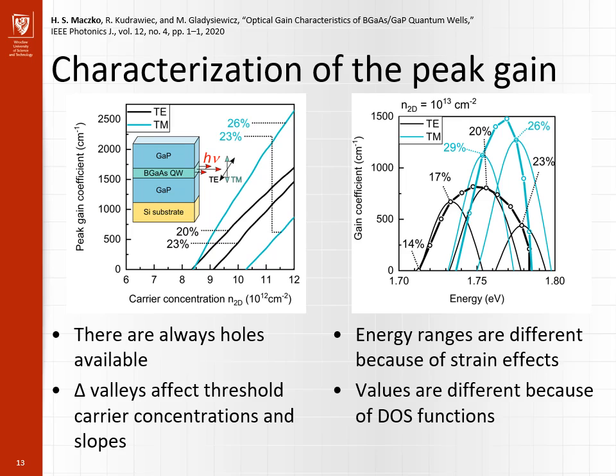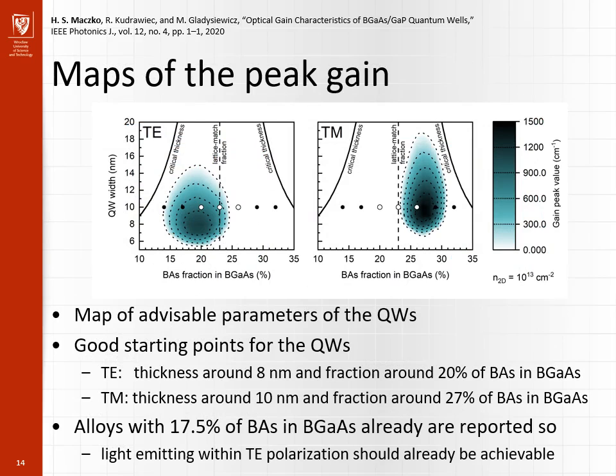However, in the case of tensile strain, delta valleys lower their energies faster than in the case of compressive strain, so the usable fraction range for transverse magnetic polarization is narrower than for transverse electric polarization. Also, because light holes have lower effective mass than heavy holes, the energies of TM gain are generally higher than those of TE gain. The final description of this system is presented in peak gain maximum for both polarizations separately.